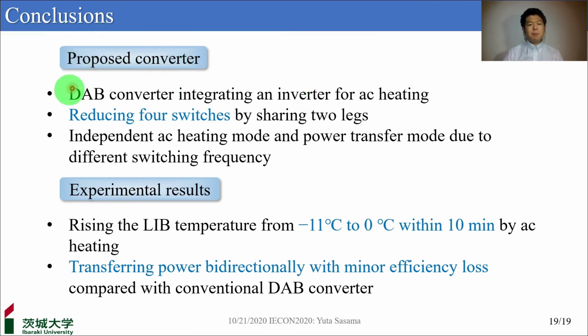In this presentation, I propose the DAB converter integrating an inverter for AC heating to improve the driving distance in cold climates. By sharing two legs, four switches can be reduced. This converter operates either in the AC heating mode or power transfer mode, and by operating the two modes with different switching frequencies, the two modes will not interfere with each other. I showed some experimental results. Our results indicate the following. First, the battery's temperature rose from minus 11 degrees to 0 degrees within 10 minutes by AC heating. Second, the proposed converter transferred the power bidirectionally with minor efficiency loss compared with the conventional DAB converter.